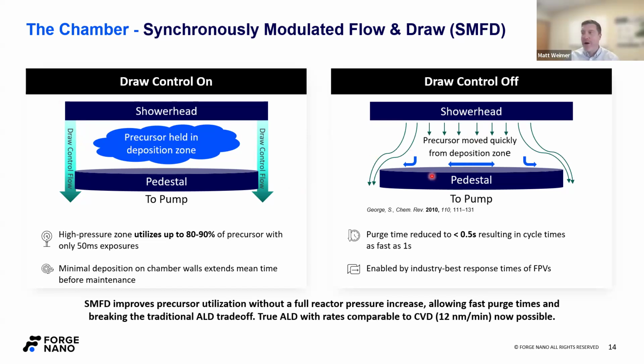We're always pumping on the chamber with a turbo pump, so we know we get down to base pressure quite quickly. And so, a couple of key things to think about here is we get really high precursor utilization. I think for our TMA water process, we are typically above 80%, sometimes above 90%. And for the exposure time, we're usually in the 4 to 5 millisecond range. For more challenging processes like nitrides and metals, sometimes we're up in the 50 millisecond exposure times. But because we're able to sort of circulate the precursor here, we just use much less of it. And because we have the sequence of on and off with the draw control, especially for oxides, our typical purge time for each half cycle is around a half a second.